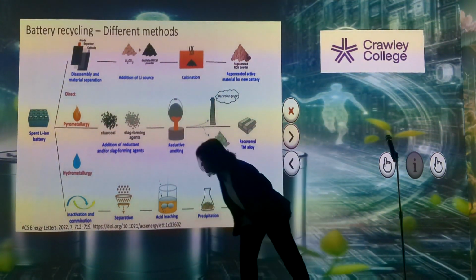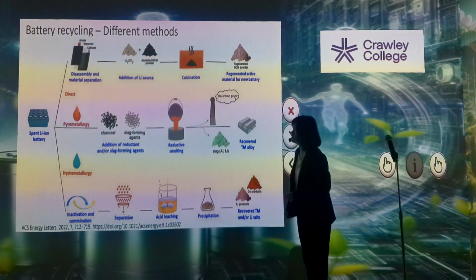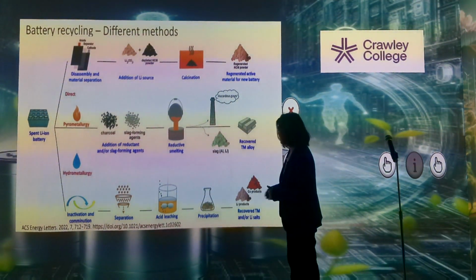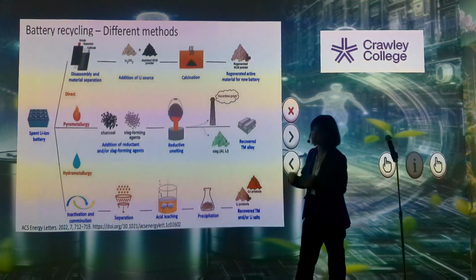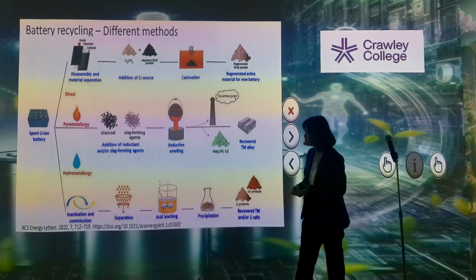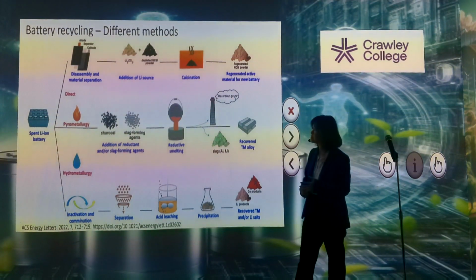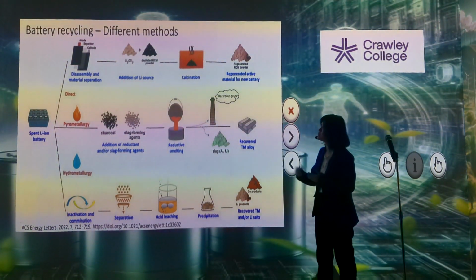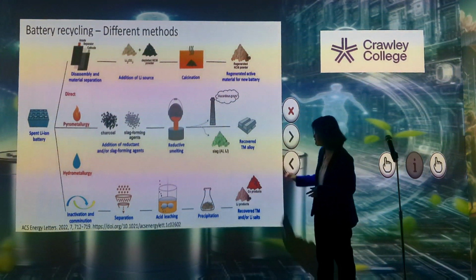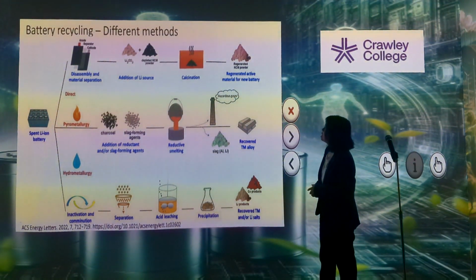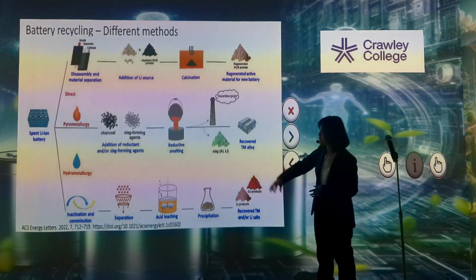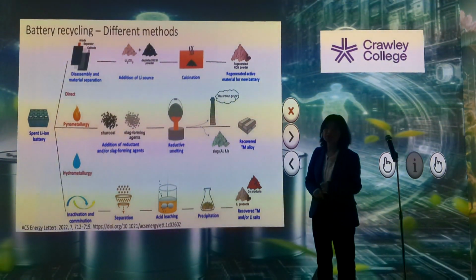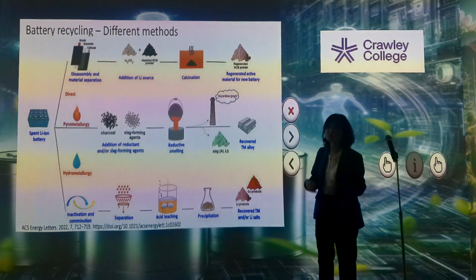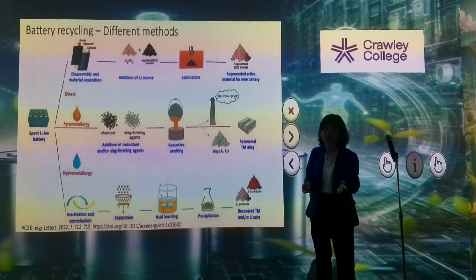This is the hydrometallurgy method, where you apply some kind of acid or alkaline medium, so chemicals, and you can have reactions at relatively low temperature, probably room temperature, or maybe below 100 degrees C, and then you can recover the materials. So this is now being applied at a larger scale. But of course, because you involve liquid solution to do that recycling process, you generate liquid waste.